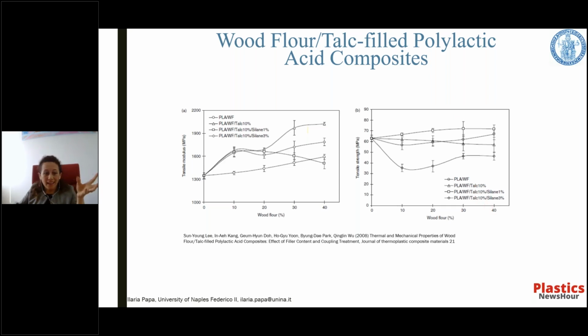For example, the talc is normally used together with the wood flour with a percentage of 13% in weight in order to improve the mechanical properties of the compound and to improve also the coupling between the polymer fibers and other particles. Suitable coupling agents are usually used. The literature reports results relating to the characterization of a composite prepared by mixing in the melt state, so in the extrusion, and containing different percentages of powders.